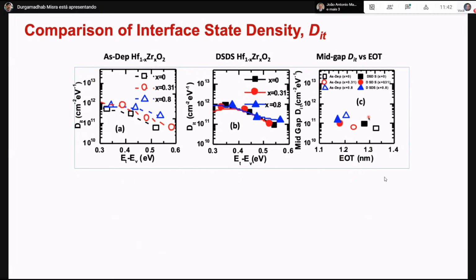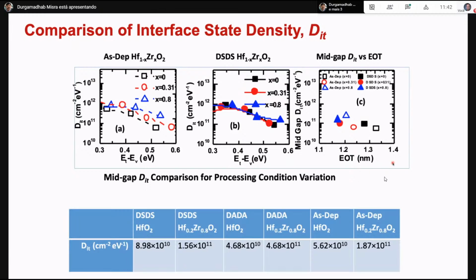But here we see that hafnium oxide still does a little bit better in terms of EOT as a DSDS process. Then we can look at the DADA process and also the DSDS process. In some cases, it still has to be optimized. But the DSDS process is much lower, 1.56 to 10 to 11, whereas DADA is much higher. We discovered that, and then we reported and published this work.